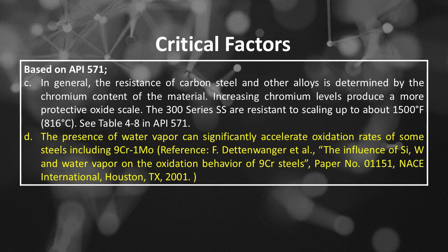Number D, the presence of water vapor can significantly accelerate oxidation rates of some steels including 9Cr-1Mo. Reference: F. Dettenwanger et al., The Influence of Si, W and Water Vapor on the Oxidation Behavior of 9Cr Steels, paper number 01151, NACE International, Houston, Texas, 2001.